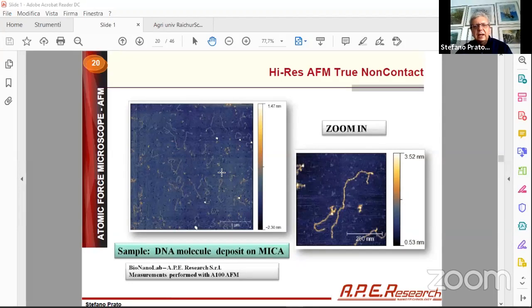related also with resolution. For example, this is a single strand DNA molecule on top of a mica sample. Okay, so this molecule, if you do a cross section here, is 1.2 nanometers tall. So it's very, very small, and it's very sensitive, because if, for example, during the scan you touch it, you just move it. Okay, this is an example. You see here, you have a lot of those.